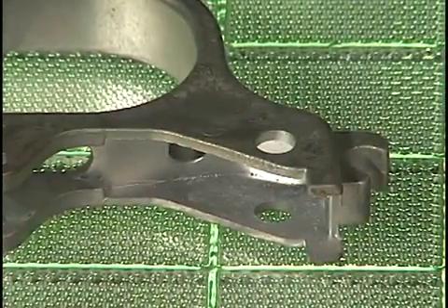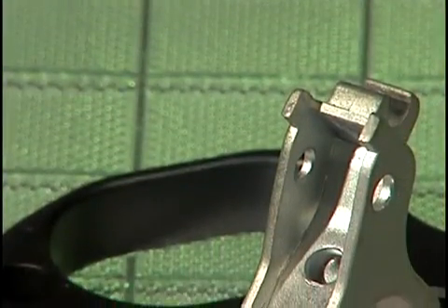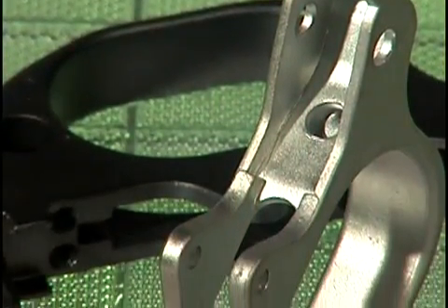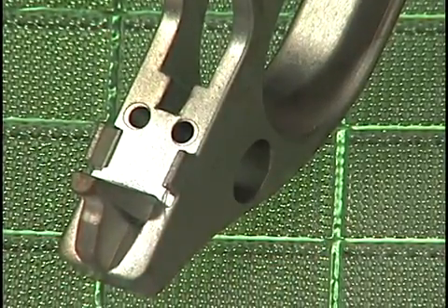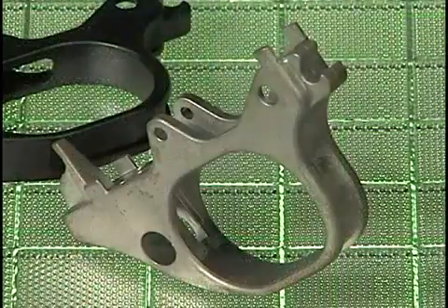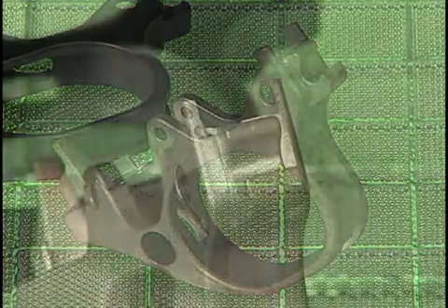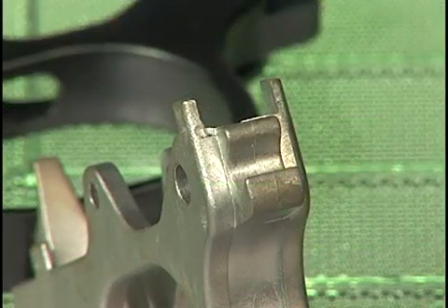Made to a density of 7.4 grams per cubic centimeter, the 3.1-ounce MIM steel part has an as-sintered tensile strength of 94,250 psi and a 58,000 psi yield strength. The part is held to critical dimensions of plus or minus 0.005 inches.